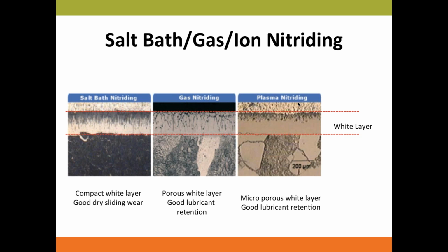There are some debates. People say it's good for lubricants because the lubricant goes into the little pores and creates better lubricity. So it kind of depends on the application. With plasma, because you can change the gas and also lower the temperature, the pores in the white layer are generally smaller compared with gas nitride, but the salt bath can create a very compact white layer.